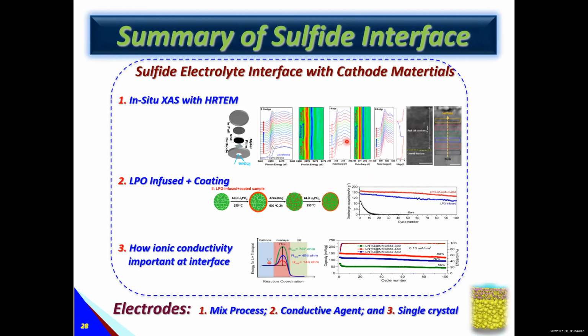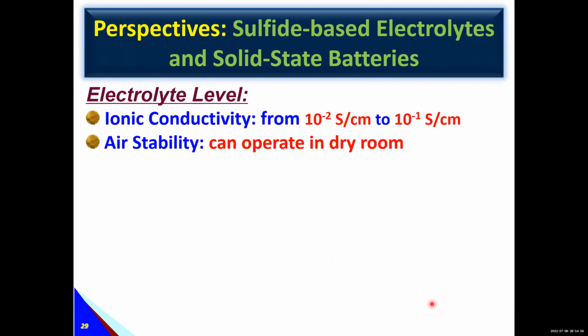This study tries to understand what happened at the interface. Another one is that coating is important for sulfide-based electrolyte. And also the ionic conductivity at the interface is very important for lithium transport. Also, I gave one example, single crystal is also important. So for sulfide-based electrolyte, many people work on that. We try to continue to increase ionic conductivity from 10 to minus 2 to 10 times higher at the electrolyte level.